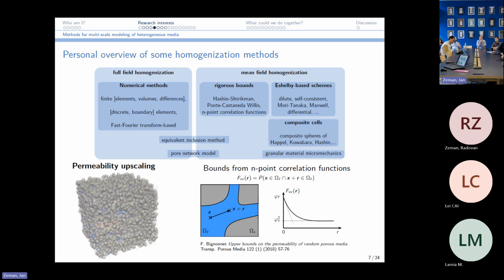And then we do that for third order information, so 3 points. And then for permeability, as opposed to what is done in elasticity, we need additional information, which is the probability that 1 point is in the fluid, the second point is on the solid-fluid interface, and the third point is also on the solid-fluid interface. And it turns out that with very involved statistical information, which is not so easy to compute, you get a bound which is not so nice. You give a lot of effort, and the result is not as nice as what you have for elasticity. So it's much harder to upscale permeability than elasticity.